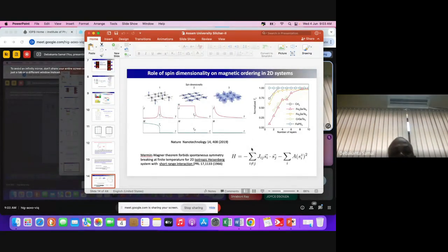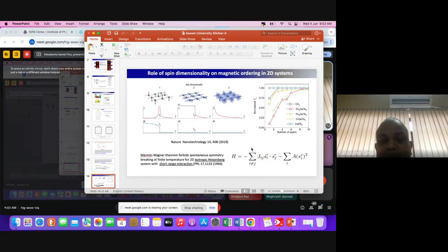What I was talking about yesterday is that we are working on layered materials, one-layer or two-layer materials. I was talking about this very famous theorem, the Mermin-Wagner theorem, which tells that if you have a two-dimensional lattice, that means atoms are in two dimensions, consider it as a paper where atoms are sitting, and you put spins at each atom, because each atom has some unpaired electrons, which give rise to spin. If you put a Heisenberg spin, it has three components, as I mentioned earlier: Sx, Sy, Sz.